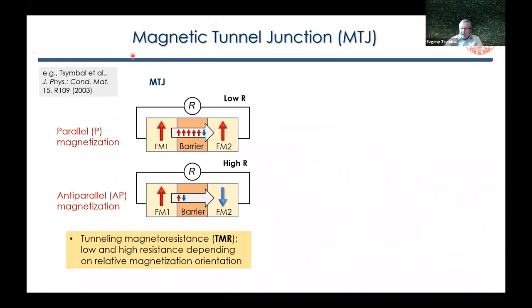So let me briefly describe the concept here because it will be relevant to what I'm going to discuss next. So the idea of magnetic tunnel junction is to have a system where we have two thin film ferromagnets which are separated by an ultra-thin barrier layer such that if you apply bias voltage, we can have a tunneling current between these two ferromagnetic metal electrodes. So the essence of magnetic tunnel junction and the importance of magnetic tunnel junction is that the resistance of this junction depends on whether you have parallel or anti-parallel aligned magnetic electrodes. And this effect is known as tunneling magnetoresistance.